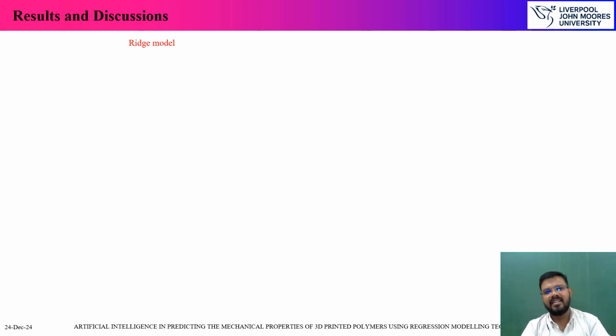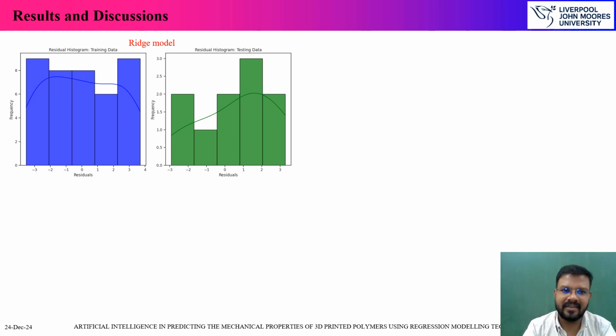Now, having said this, the residual histogram after the analysis between the training and the test data, at a split ratio of 80 to 20, we could see a slight skewness towards the negative in the initial stages of the training data, which is clearly telling that the model is slightly over predicting the result. And if you see the residual histogram of the testing data set, it is slightly skewed towards the positive side, which leads us to a conclusion that it is slightly under predicting the value. This was our first Ridge model, wherein only three of the four factors were selected.